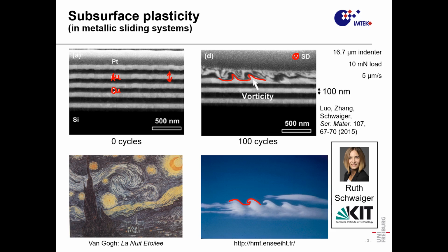And it's very difficult to believe that this Kelvin-Helmholtz type of instability would also occur for metals that, if you were able to describe them with a viscosity, would certainly not be in a high Reynolds number limit, because the viscosity would be very high. So we thought there must be some sort of atomic scale mechanism that leads to the formation of these vortices, and started to use computer simulations to look at this. And I would like to tell you now what we find and what we had to do in order to reproduce these vortex patterns.